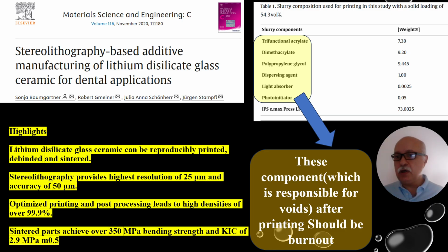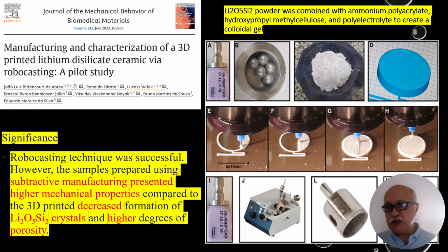Experimental slurry contains about 30% additive for reaching the printing requirements. This research obtained 90% density, 350 megapascal bending strength, and 2.9 toughness. Other printing technologies like robocasting cannot reach the strength of conventional glass ceramic yet.